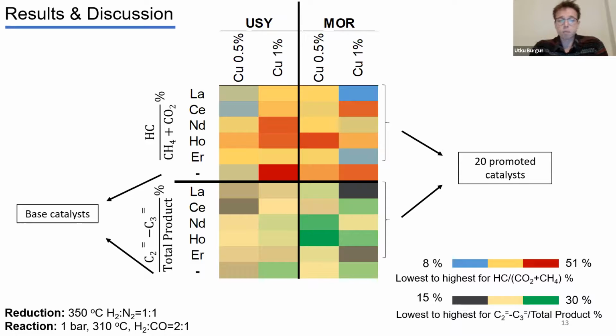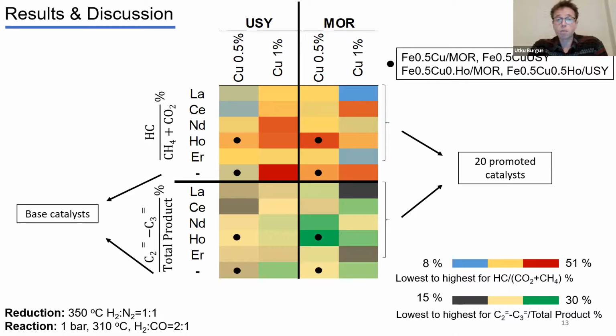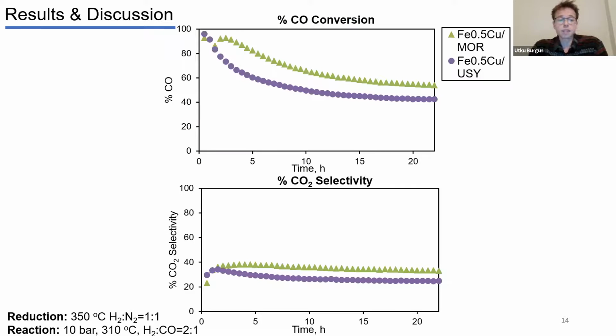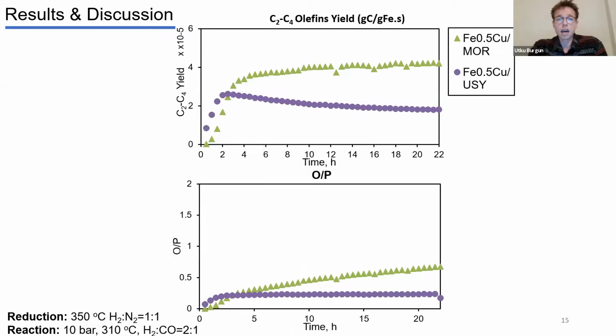And here we have selected 4 catalysts, 2 of which are base catalysts of 0.5 copper promoted iron catalyst, and the other 2 are holmium promoted iron copper catalyst. And these 4 catalysts were then tested in the pressurized test system. In the pressurized test system, the reduction and reaction conditions remained the same, but the reaction pressure increased up to 10 bar. Here, it can be seen that using the mordenite support increased the carbon monoxide conversion and CO2 selectivity with respect to the ultra-stable Y-supported catalyst. And also the light olefins yield and olefin-paraffin ratio increased on the mordenite-supported catalyst.